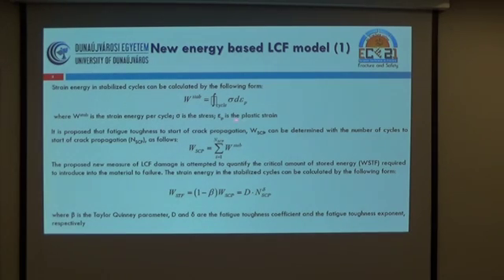The strain energy, once the cycles have been stabilized, can be expressed by this equation. And we propose that the fatigue toughness to start of a crack propagation can be determined with the number of cycles to start of the crack propagation as it is seen here. So, the proposed new model deals with quantifying the critical amount of stored energy required to introduce into the material to the failure.